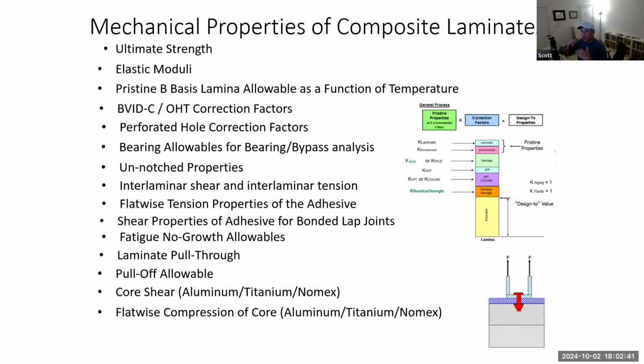There are a lot of joints where the parts are bonded together, not bolted, with some kind of adhesive, and we need to understand what the shear capability of that adhesive and the joint is overall. Fatigue no-growth allowables. Fatigue is a different animal when you're dealing with composites versus metals. It's a much more complicated process. Some companies use very simplified approaches to determine the fatigue microstrain allowable of a laminate. But basically, it's a coalescence of multiple cracks that form together and then go into one big crack. Sooner or later, that one big crack will cause failure. It's basically micro-cracking continuously growing across the matrix and the fibers.